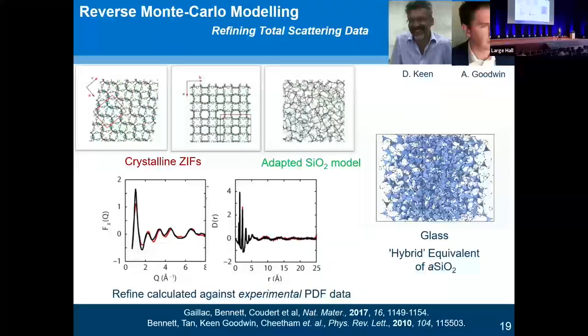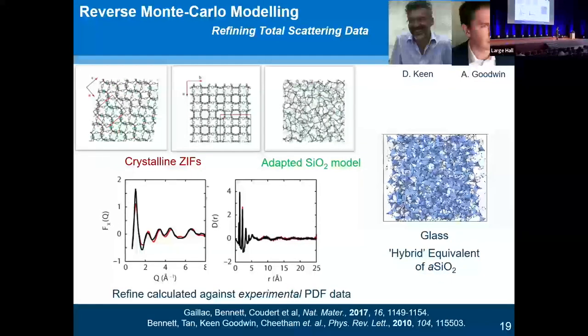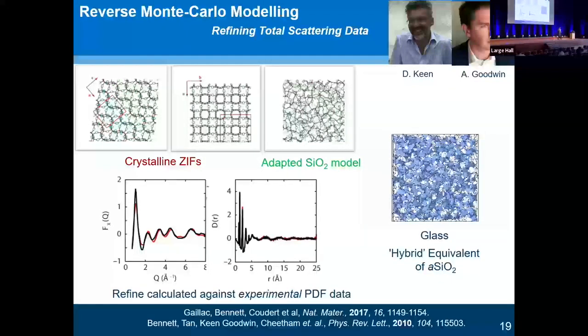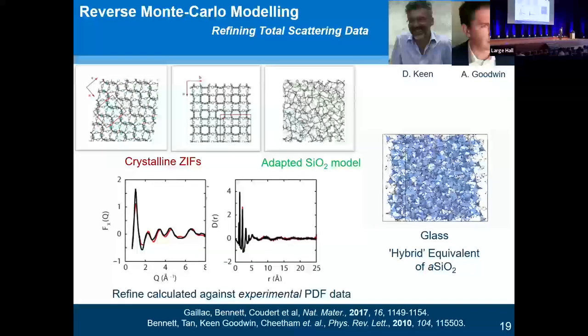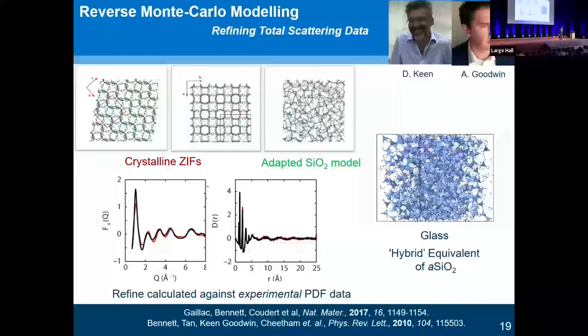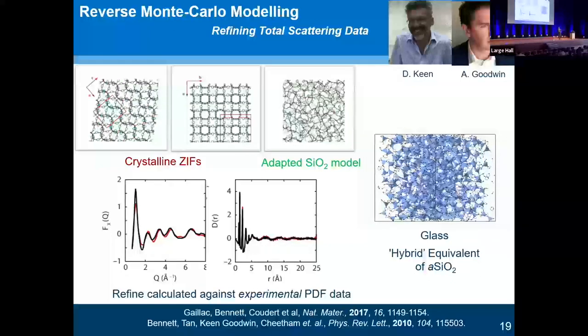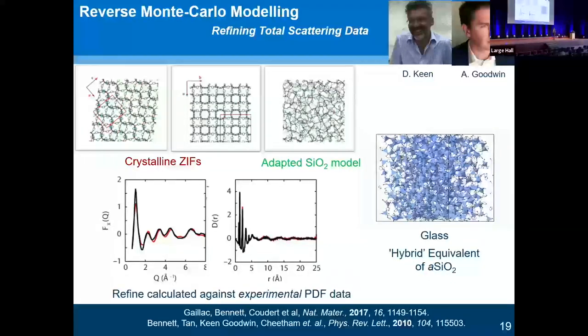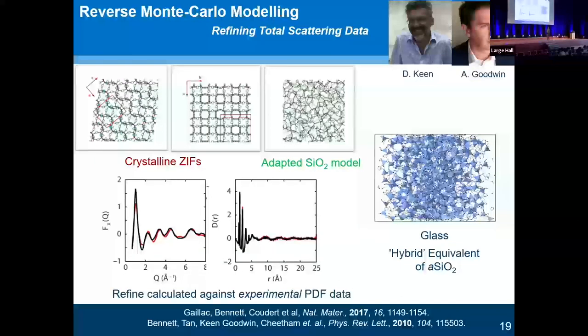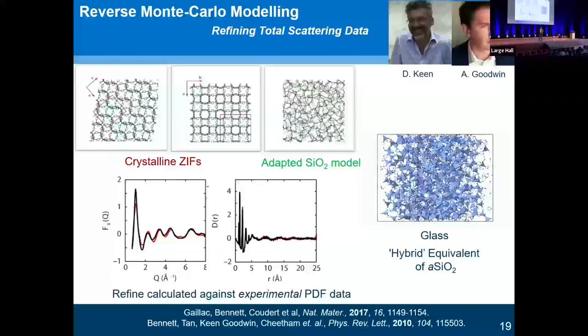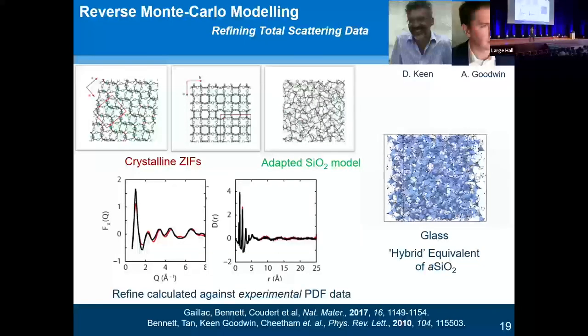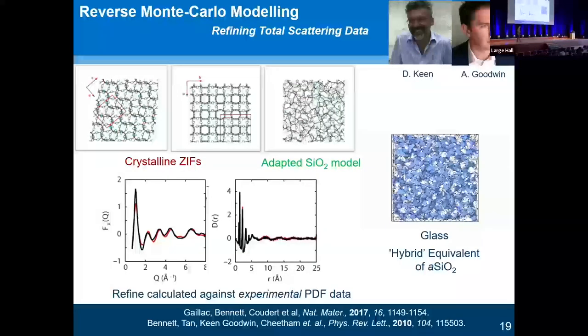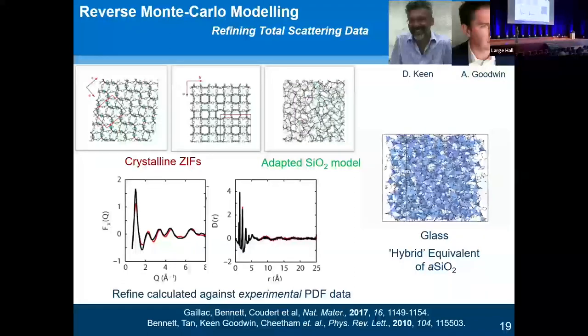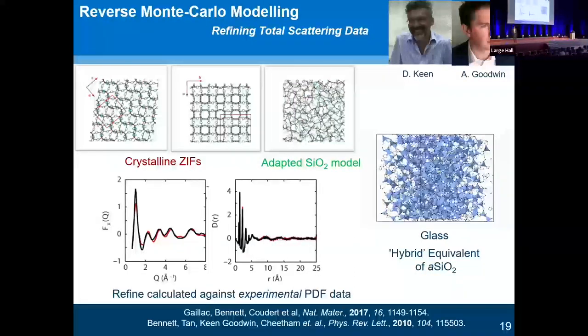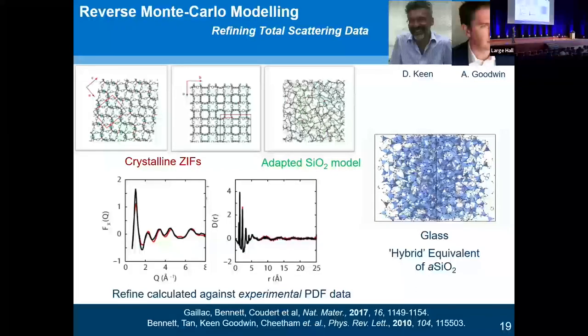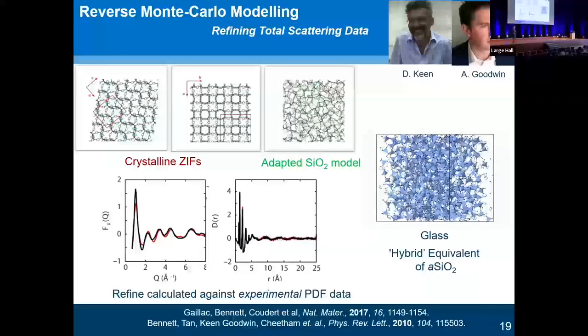So evidently with a glass ZIF, the first thing you think is, okay, I'm going to take a crystalline one. But in actual fact, it doesn't matter how many you take or which ones you take, you can't reproduce the experimental data. The only way you can do that is by taking an old model for silica glass, for pure SiO2, replacing the silicon with zinc, replacing the oxygen with imidazolate, and then expanding it slightly. Once you do that, you come up with a configuration which has an excellent agreement to your experimental data. And that's why we're so comfortable in calling these glasses a hybrid equivalent of amorphous silica.